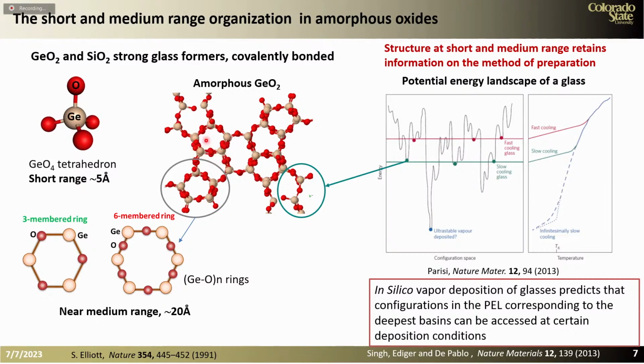And this is, in the amorphous oxide, these rings are of different sizes. Now, in an amorphous material, we lack the periodicity of the crystalline material, and so we say, oh, there is no order. But actually, there is some order in the oxide, and that order is at scales of a few nanometers. We call that the medium range order. Now, this order can be affected by the way the material is formed.